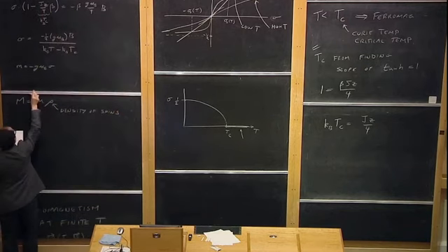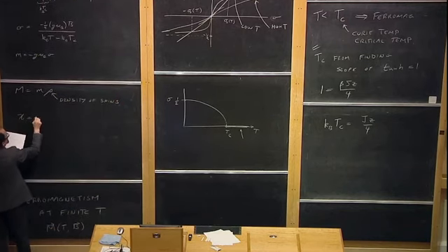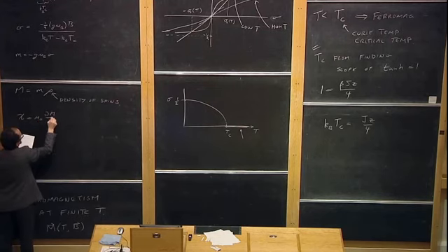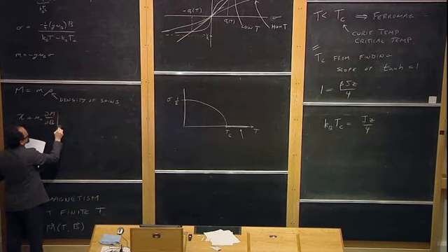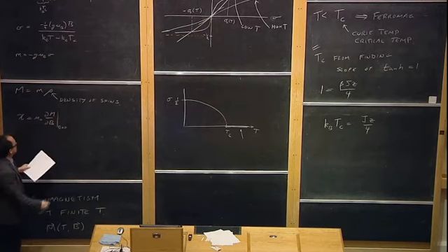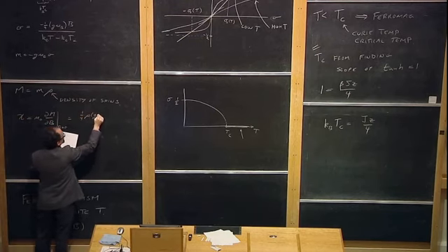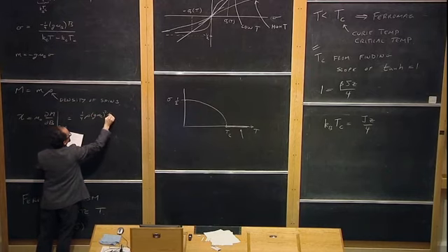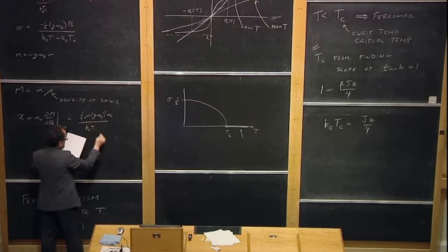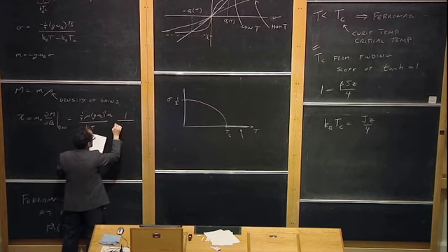And then the susceptibility will be, by definition, mu naught dM/dB at B equals 0, which, plugging in a couple of lines up here, gives 1/4 rho g mu_B squared mu naught over k_B T times 1 over 1 minus T_c over T.